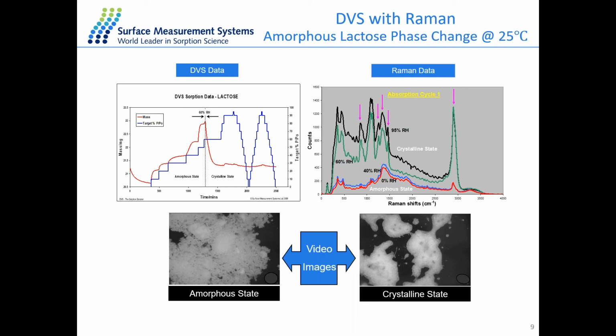We also use the Raman spectrometer to collect the spectra. Here are the data. At 0 and 40% RH, there are just some broad peaks in the Raman spectra, confirming the amorphous state of the material. Above 60% RH, there are some new peaks showing up here, and these new peaks are because of the crystalline state of this material. So this Raman spectra confirms our conclusion from the DVS data that the sample goes through the amorphous to crystalline phase change at 60% RH. So the combination of the Raman, the DVS, as well as the video images gives us a full idea about the solid characterization of a certain kind of material.